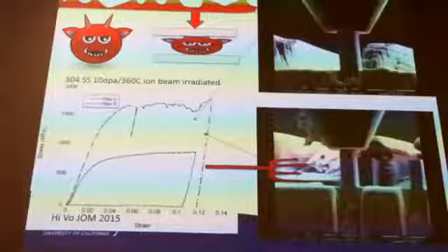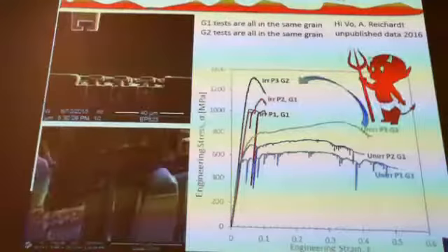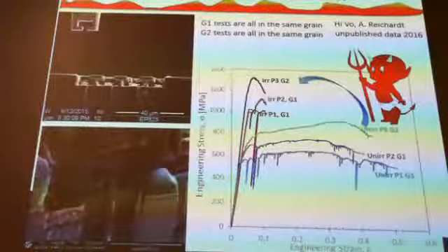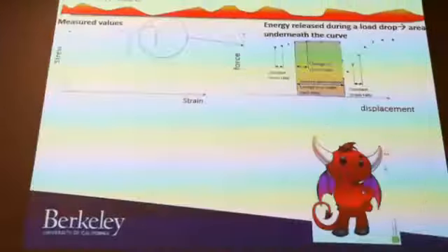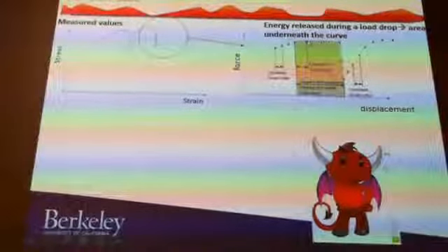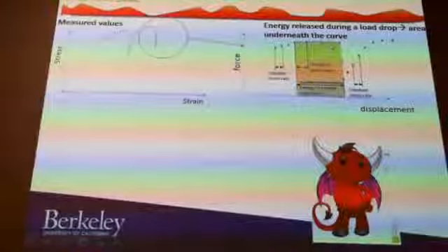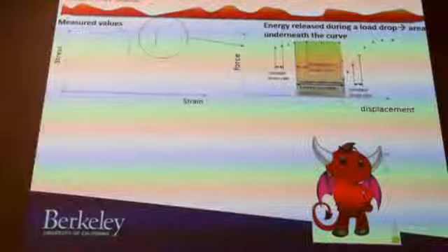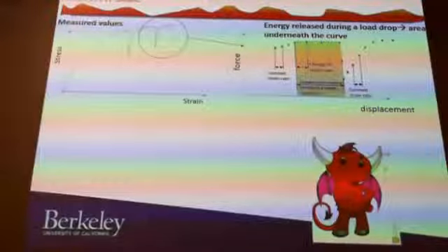What the actual physics is, is actually a change in displacement. A sudden change in displacement is the actual physics because it's suddenly longer. But because the tool has a feedback loop and slack in the hole, you have to accelerate masses of the tool and so on. That leads to this drop at the end, and that marks the end of this behavior. But fundamentally, it is the dislocation running through the system.